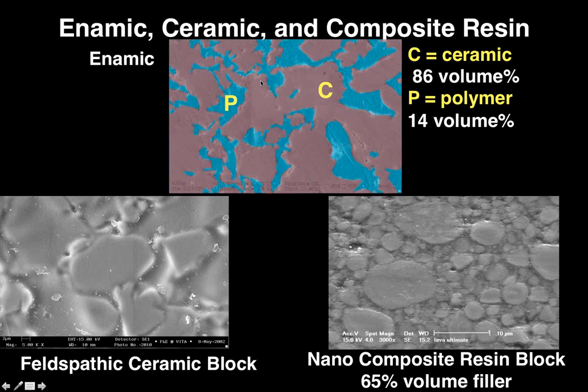And that was one of the issues during development. Would there be a debonding of the polymer from the ceramic? We did many tests, boiling tests, aging tests, thermal cycling tests, and there wasn't this debonding. Because this was a completely new material, it ended up being a very long development process. There was lots of discussion about properties, and that's one of the reasons why it took so long to get this material out there on the marketplace.